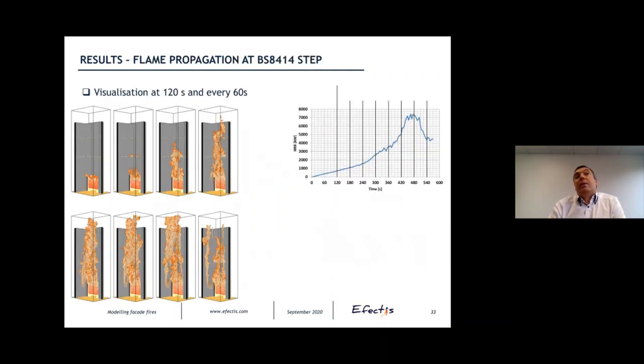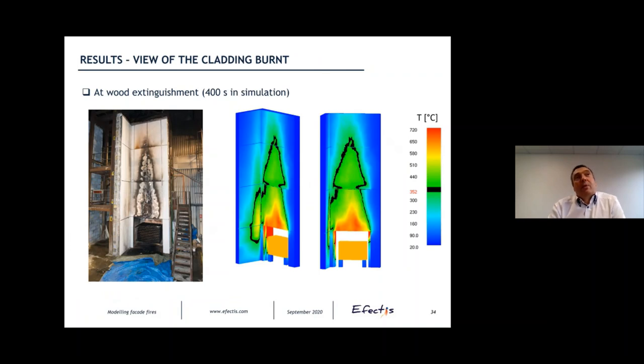Then we make a calculation at BS8414 test, and we compare with the experiments, and this is the calculation. In this case, we see a very typical downward propagation that is very characteristic of this kind of materials, and that was visible in the end in the real fire. And we compare with the experimental results of what has been done at BRE at that time.